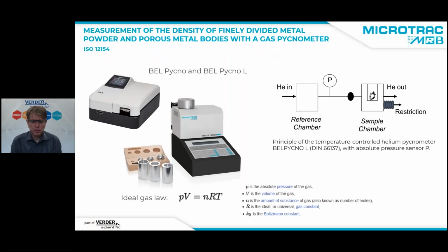In addition to particle size and shape, MICROTRAC also offers measurement of the density of the powder. Here we have an instrument called BEL Pycno, and what we do basically is we give a certain mass of powder into a sample chamber. Then we load the sample chamber with gas, and the pressure that we measure tells us how much volume in this sample chamber is occupied by the particles. So this is typically done with helium. So this is a helium pycnometer.